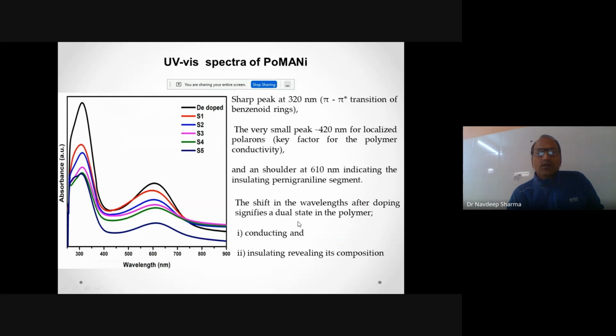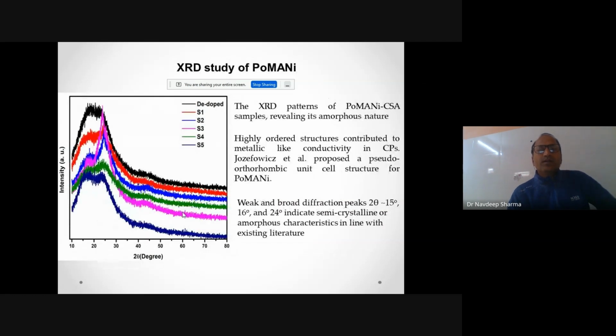and the shift in the wavelength after doping signifies a dual state in the polymer, that is conducting, revealing that in comparison to the de-doped state, there is a formation of the conducting polymers in the proper way. This is also confirmed with the help of our XRD study of poly(ortho-methyl aniline).